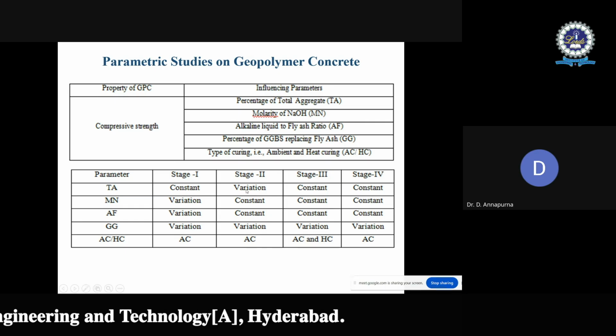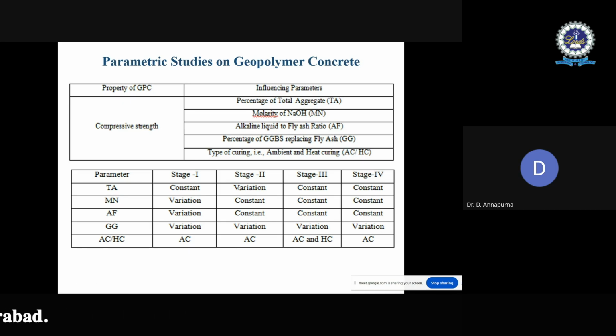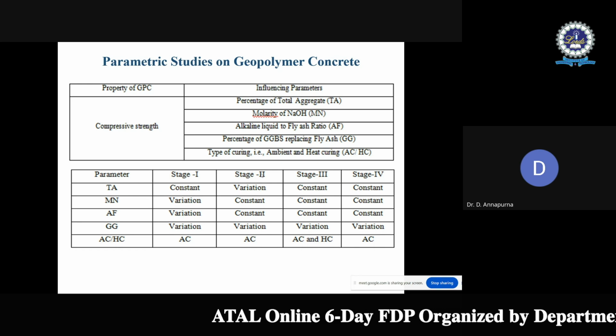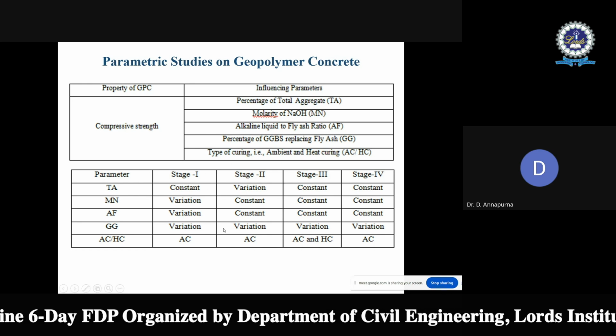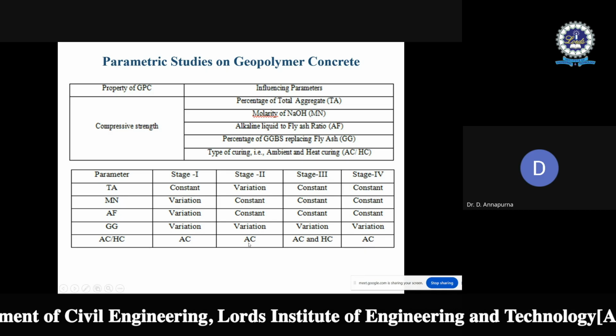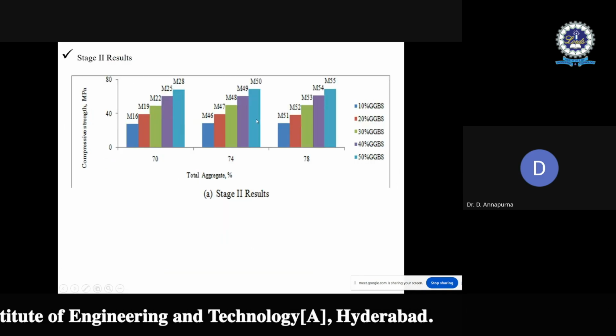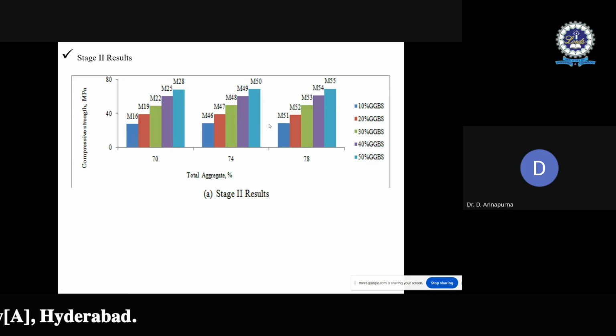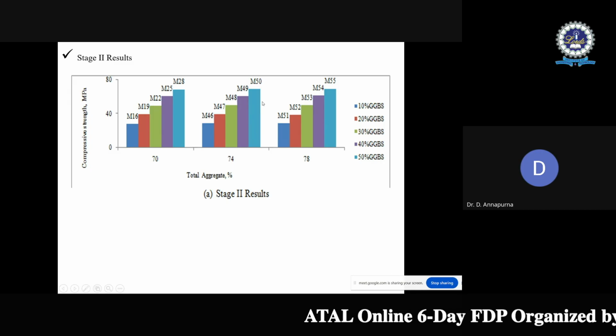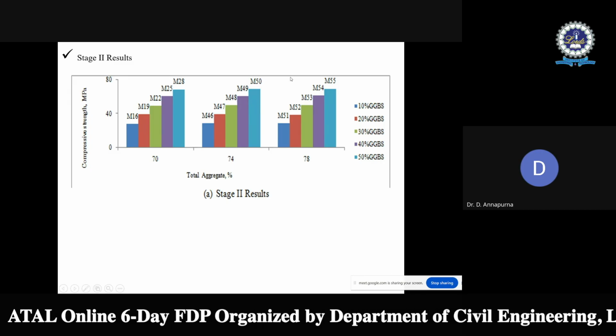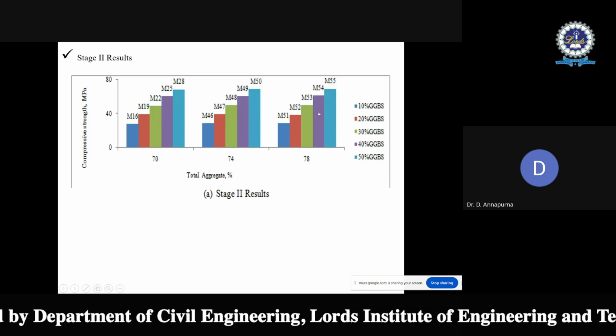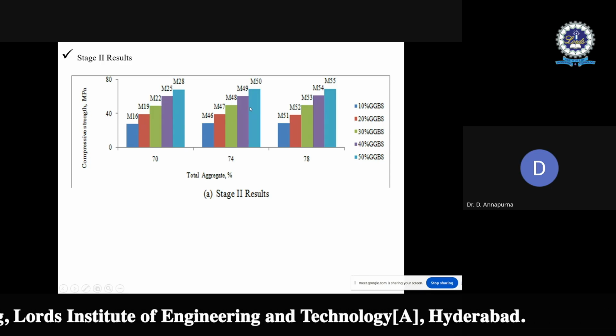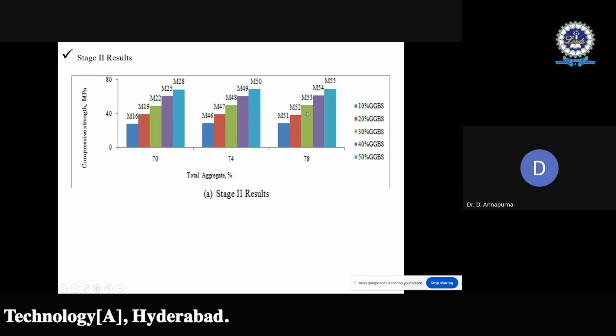Now we want to check the variation. What will be the influence of variation of total aggregate on the compressive strength? So now the variation is taken as 70, 74 and 78%. Again, only ambient curing conditions are considered in the geopolymer concrete. The next stage of investigations reveals that as the total aggregate proportion increases from 70 to 78%, the compressive strength increment is only around 3 to 4%. For different GGBS combinations, it is not showing much influence on the compressive strength.